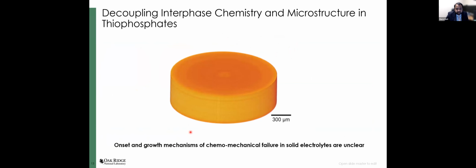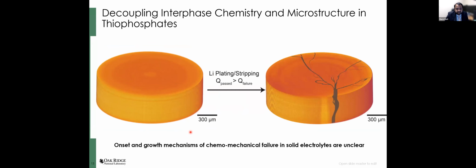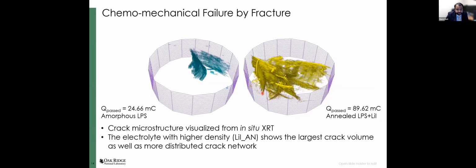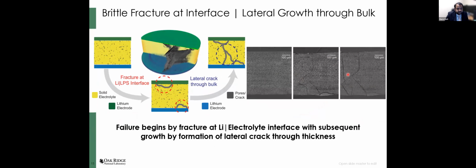Some of the other things that we studied with thiophosphate materials was understanding how these solid electrolytes undergo these profound, catastrophic fractures. What you're seeing here are actual experimental images of solid electrolytes that we've measured through tomography. And you can see that depending on how the processing was carried out on these thiophosphate solid electrolytes, we see very distinct failure mechanisms. But underlying these different failure mechanisms, we were able to find a unique link that essentially gave us an idea of how fracture begins in these solid electrolytes. We were able to show that a chipping of the interface at the lithium-electrolyte boundary is how the fracture mechanism begins, followed by a lateral crack growth through the thickness of the electrolyte.